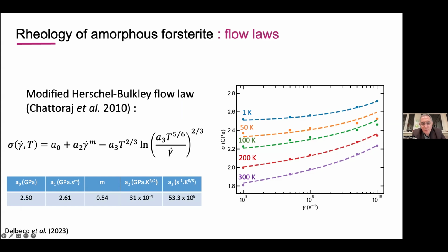I did not show you that because it cannot be compared with those experiments, but it can be compared to some other push-to-pull experiments that we did, but I didn't have time to show that. There is a small offset, and I think the reason is that the interatomic potential is a little bit too weak. So it could be very easily rescaled so that we have a really continuous description across the scales. This is not something that we did yet. We were first more interested in the mechanisms.